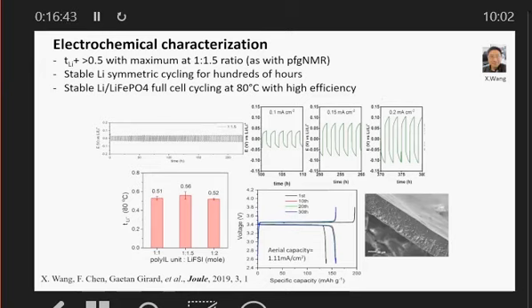So we're getting now more than 0.5, 0.56. In all three of those systems, we're above 0.5, but that 1:1.5 gives us the optimum transport number in this system. We see on the top left-hand side that the lithium symmetric cell measurements are very, very stable, hundreds of hours with low potentials. We are doing this at 80 degrees C.